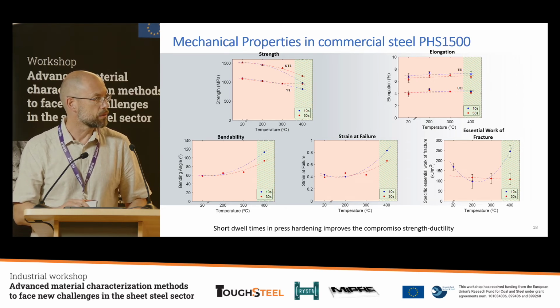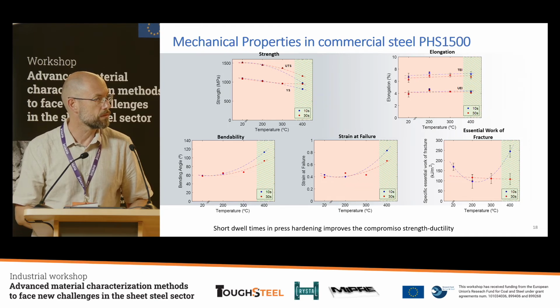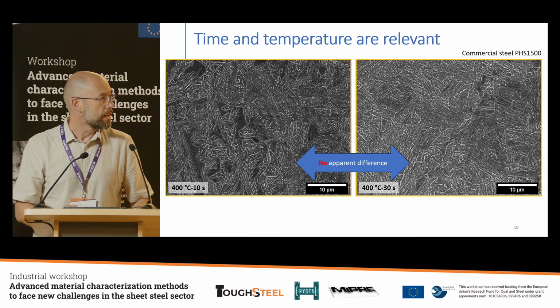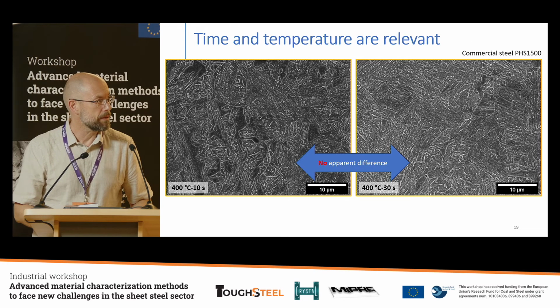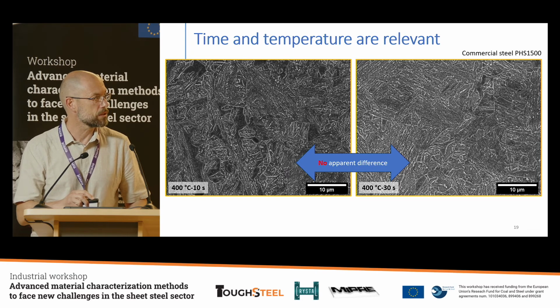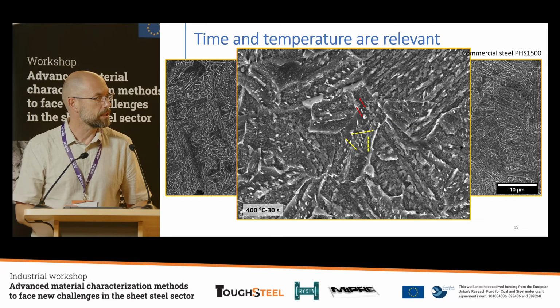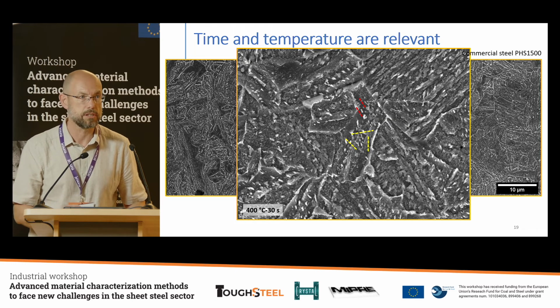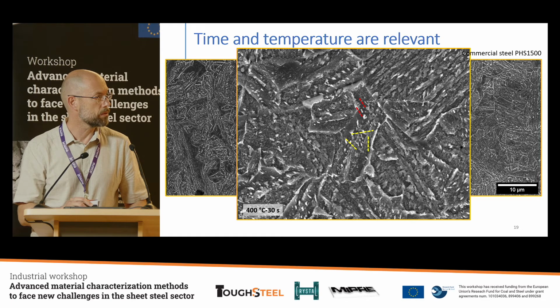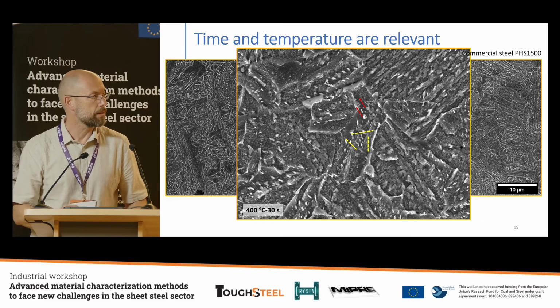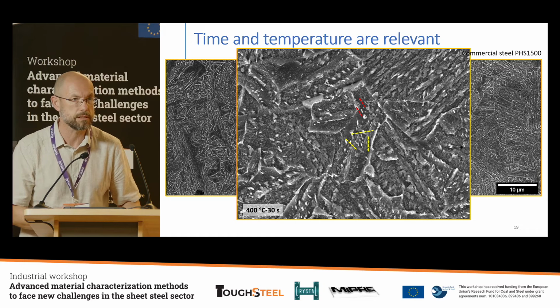And you can see the role of the dwell times, for example, with different values of properties. As I mentioned, apparently there are no differences when you have 10 seconds or 30 seconds. But when you go inside, you can see how the precipitates are distributed inside the microstructure. I put these red lines to highlight how they are oriented. When they are aligned, you have a lower bainite microstructure. When they have a random orientation, you have tempered martensite.